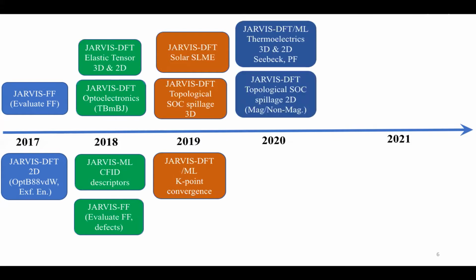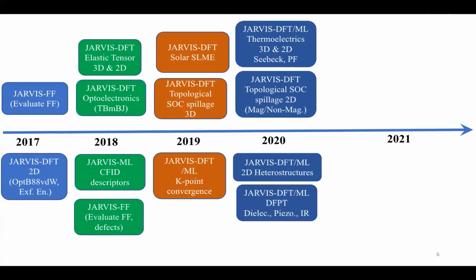And then we extended the topological spin-orbit criteria to 2D materials, for both magnetic and non-magnetic systems. We have a 2D heterostructure app design. So using the 2D structure database, we could predict the band alignment, the lattice mismatch, etc. We extended the density functional perturbation theory database, from which we get the dielectric function, piezoelectric tensor, infrared intensity, and other key properties. We also developed an electric field gradient database, from which we can calculate nuclear quadrupole resonance and nuclear magnetic resonance spectra.